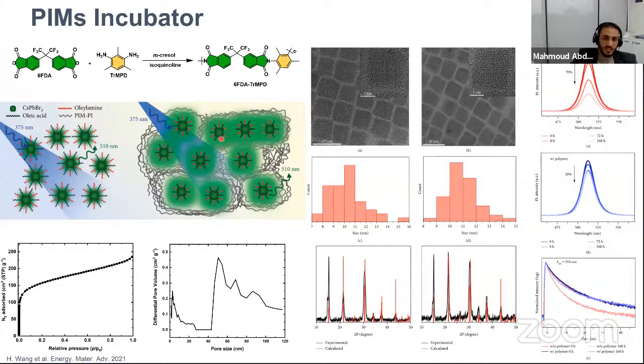And the last application, which is not very related to oil but is also a new application I would mention, is using PIMs as incubators. For electronics, there is a type of quantum dots and perovskites generated, and it's one of the most promising materials for the future. But they have a problem in terms of air sensitivity. They are highly air sensitive and could decompose fast. So we thought of putting these nanocrystals inside our polymer. Our polymer is a porous polymer, so why not just make a membrane and put these nanocrystals inside?